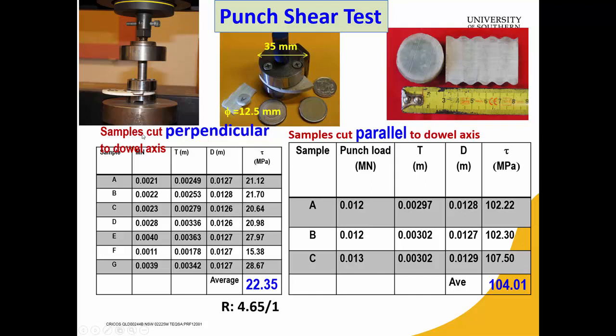As you can see here, samples cut perpendicular to the dowel axis show shear strength around 22.35 megapascal, which is this one, and the sample cut parallel to the dowel axis, which is this one, shows shear strength of 104.01 megapascal. So the ratio of sample cut parallel to the dowel axis divided by sample cut perpendicular to the dowel axis is around 4.65.